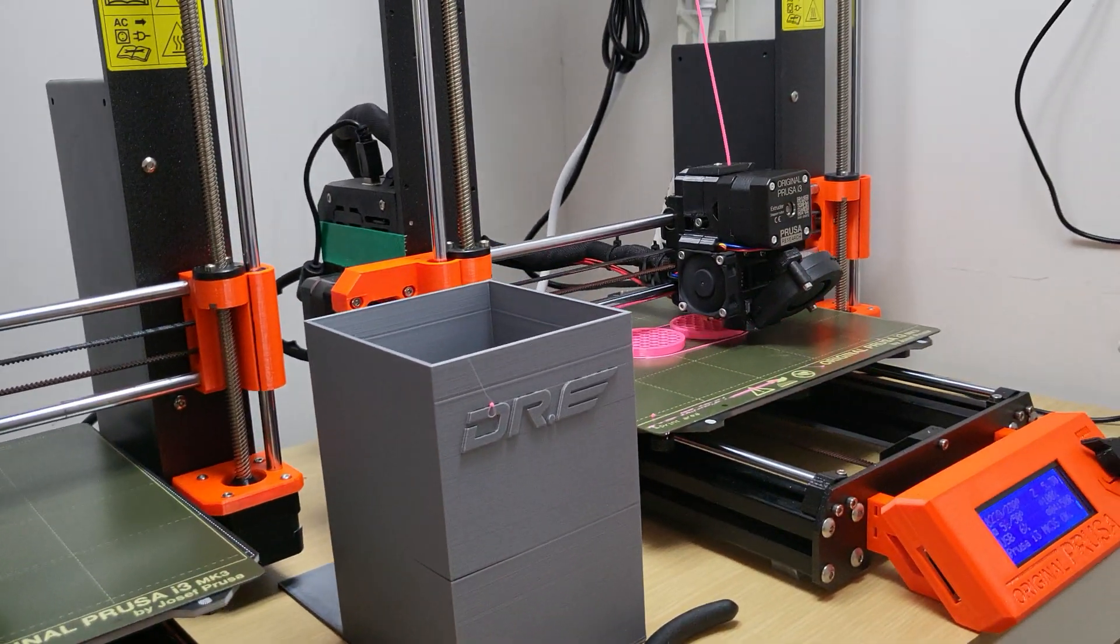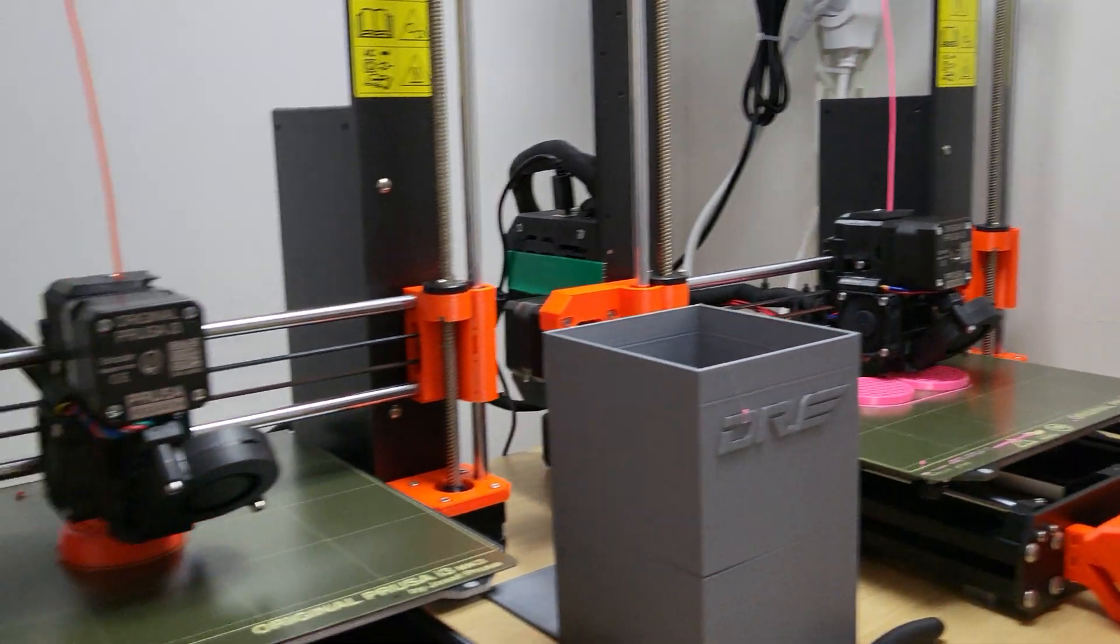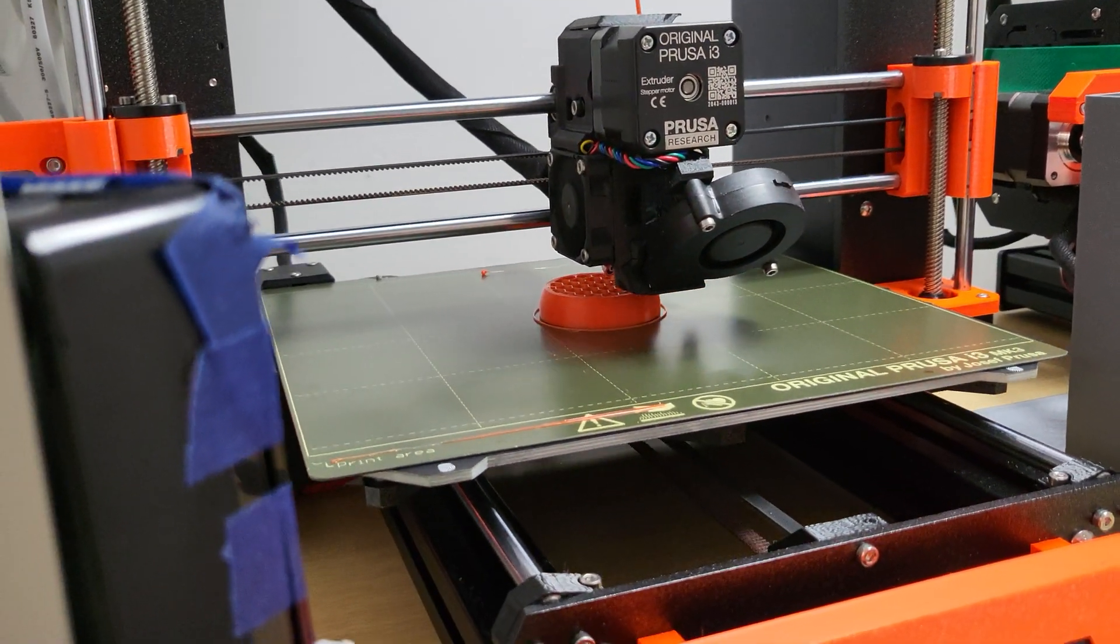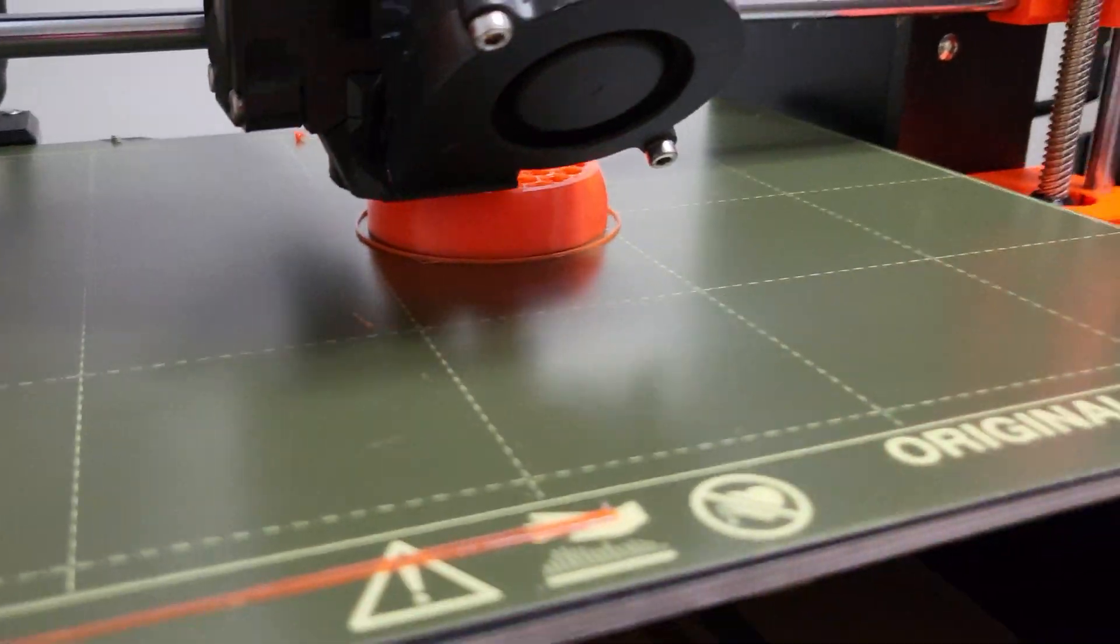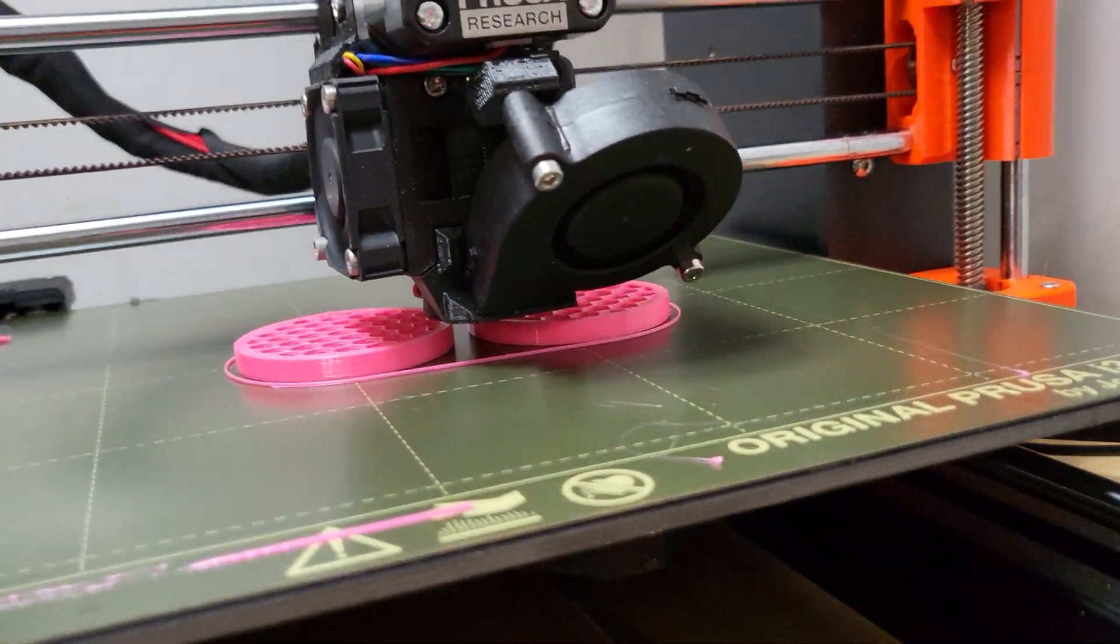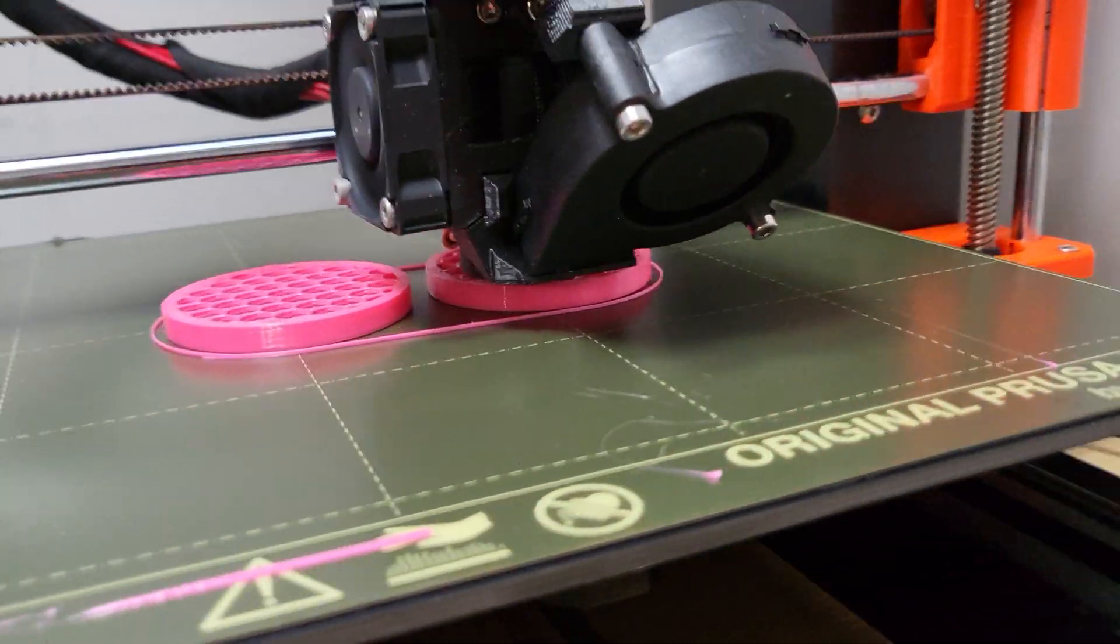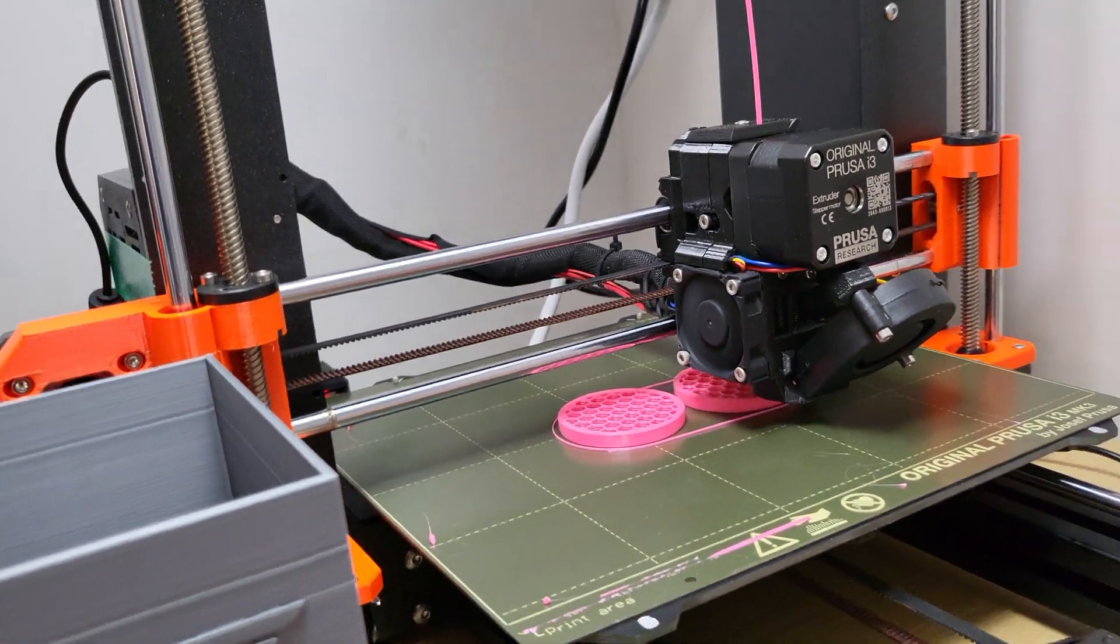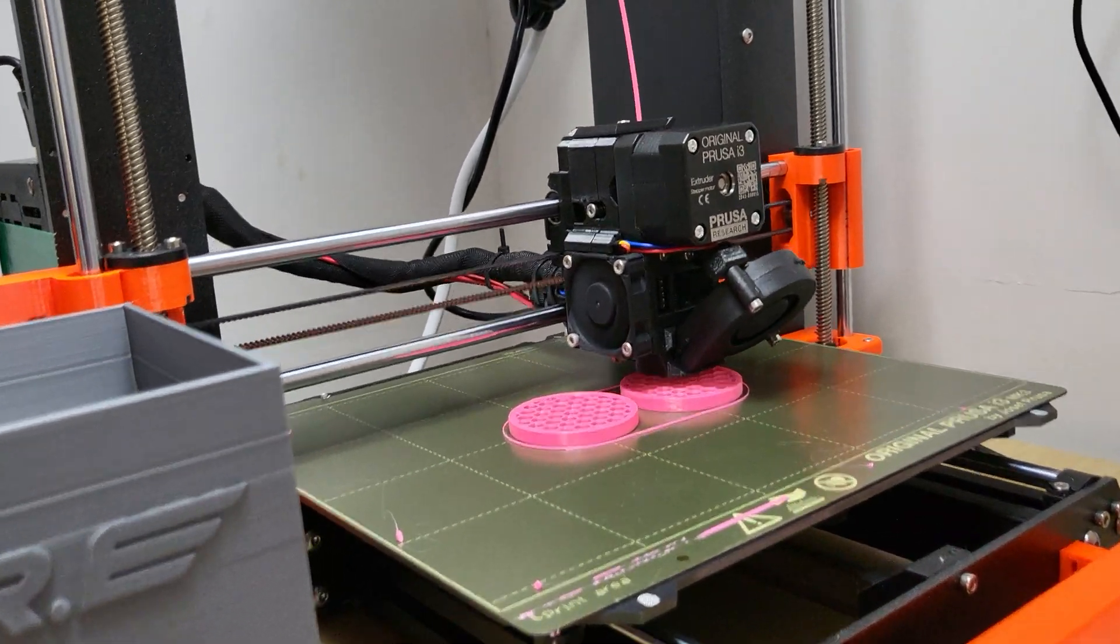Hi guys, I'm doing really well at 200 millimeters per second speeds. Look at those speeds on the display and I'm printing nearly flawless. I'm actually printing multiple objects and I was having some trouble with stringing, but now all the stringing is gone. I'm using retraction of 0.4 millimeters, which seems to have solved the problem.